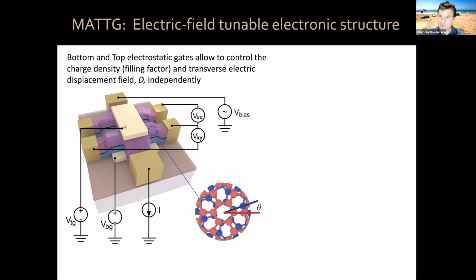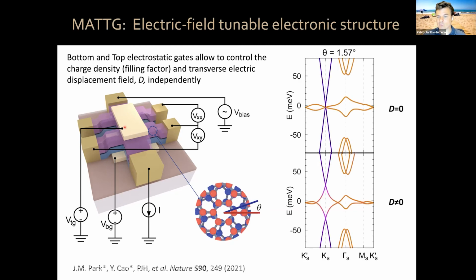gates, okay? And when we apply a finite displacement field, then we break electrically the mirror symmetry in the structure. And then we can hybridize the massless Dirac bands and the flat bands. And we can hybridize them to form this interesting electronic structure, which is tunable with displacement field, the degree of hybridization. So, okay, the first thing I want to show you is that the system is a robust superconductor.